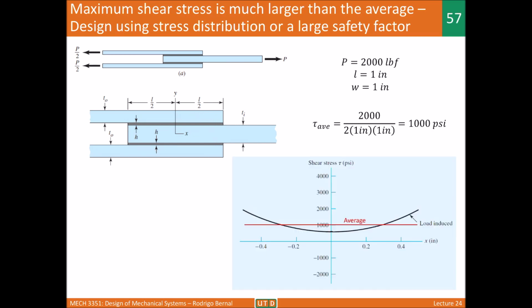If you actually make that calculation using a full elasticity theory and compare this average to what actually happens, you will see that the average, although within the same order of magnitude, actually underestimates the maximum stress that happens. And it can be almost double, and even more depending on the geometry. However, this calculation is not straightforward. It changes depending on each different geometry.